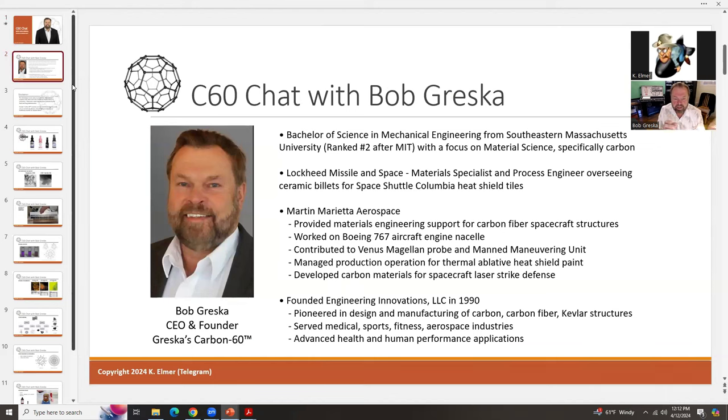But the tiles themselves are ceramic. They're made out of something like cotton candy, except they solidify it by heating it to very high temperatures, and it fuses all the fibers together. It's kind of like a bunch of fiberglass mat all fused together. So they're fairly porous, almost like a filter. You can actually pull air through it, and so they're very brittle. So when that chunk of ice hit the tiles, it broke like 5 of them.